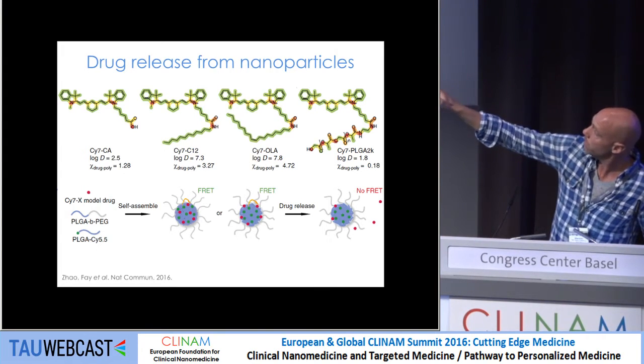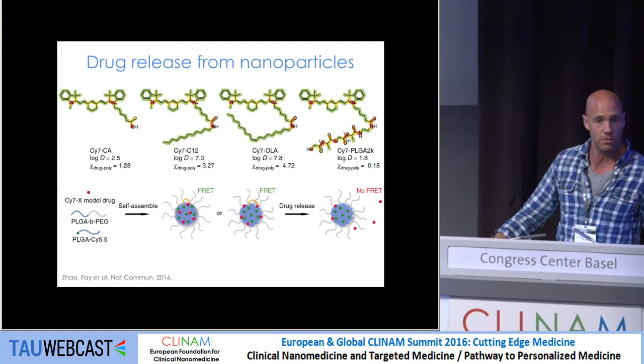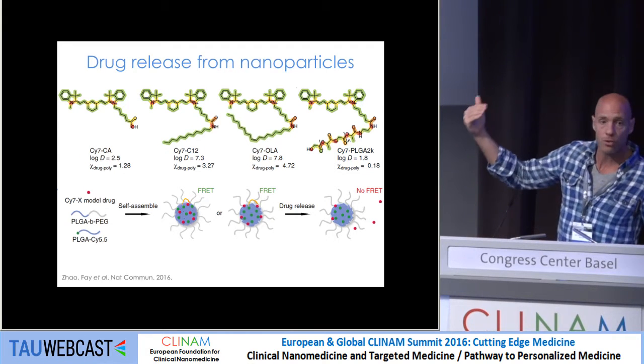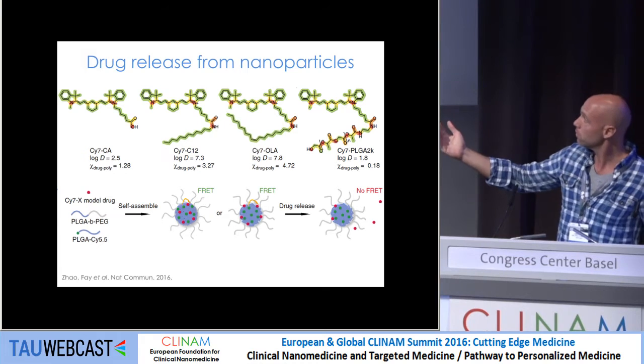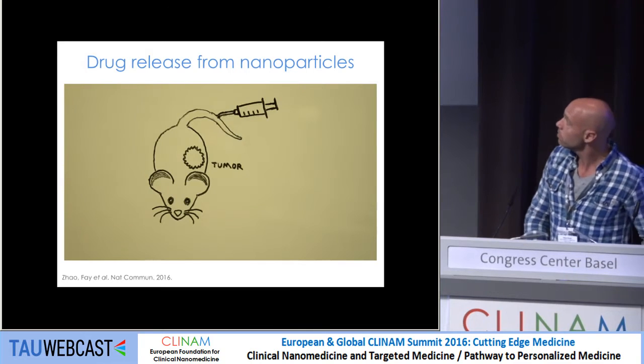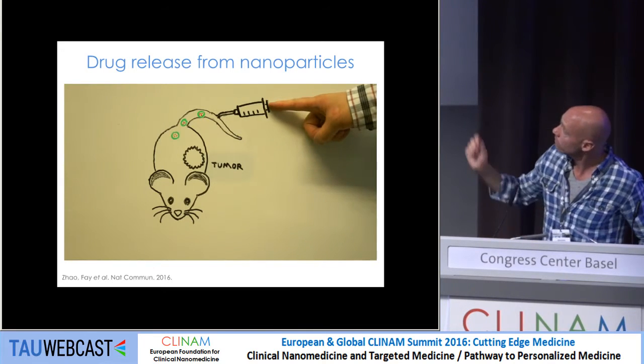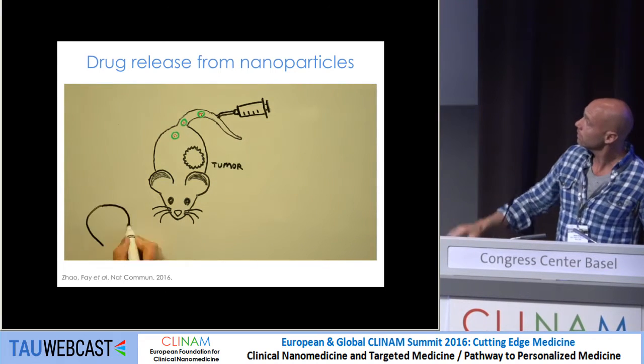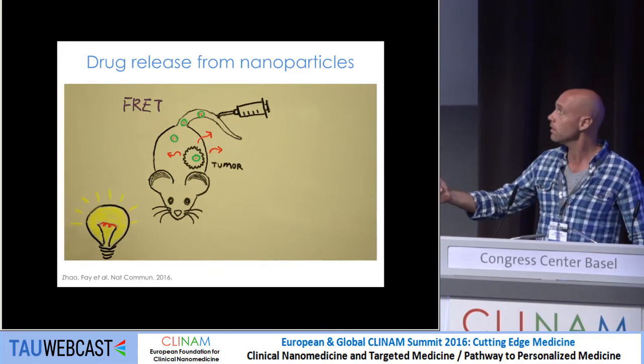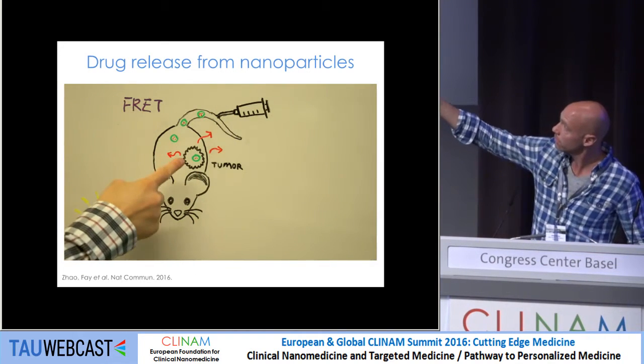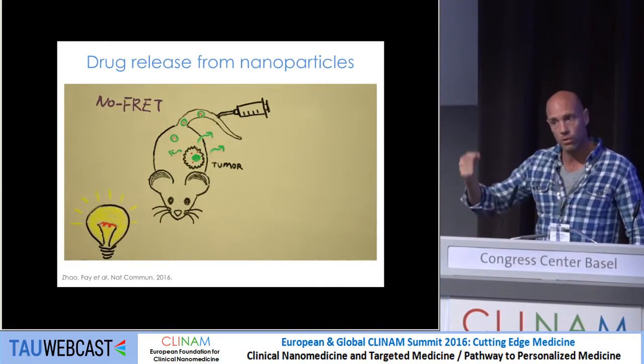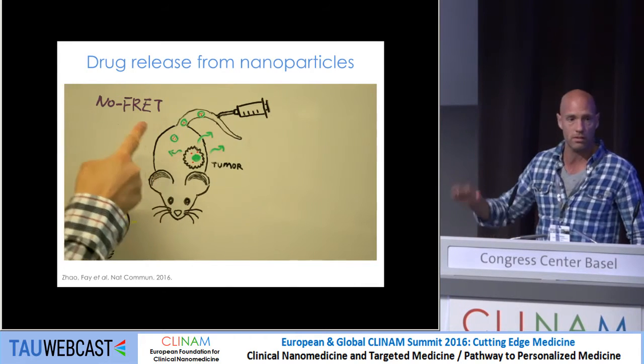On the left is the lowest compatibility, and then we started increasing the lipophilicity of these drugs. Ultimately we even added a small polymer, which increases compatibility of the drug with the nanoparticle platform. Through this FRET imaging we can look at the release of the drug. We inject these dual-labeled nanoparticles; they accumulate in the tumor. If the drug is associated with the nanoparticle, we see a FRET signal. When the drug releases from the nanoparticles in the tumor, the FRET signal disappears.